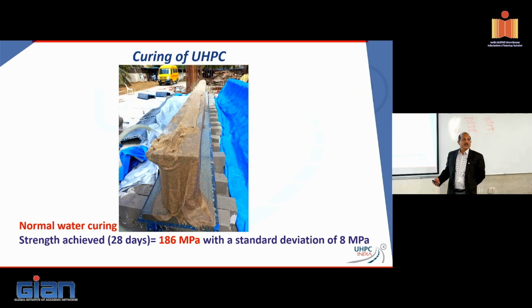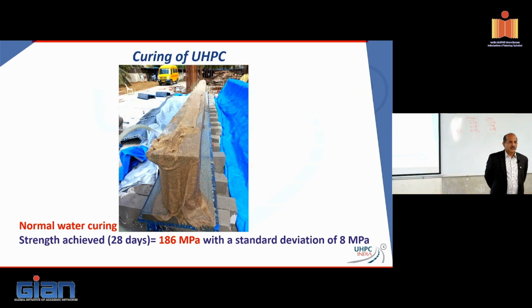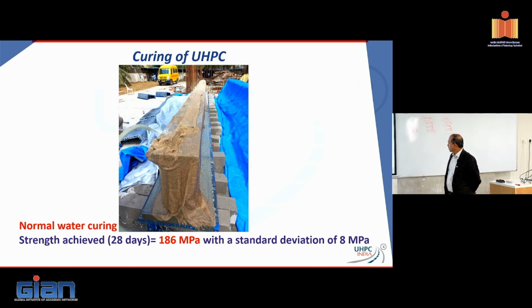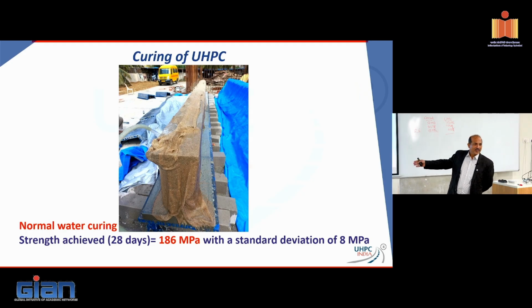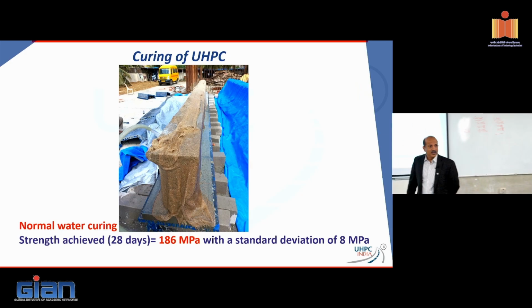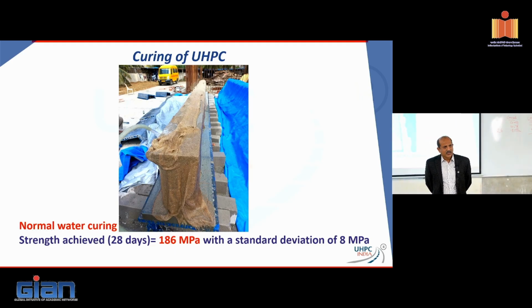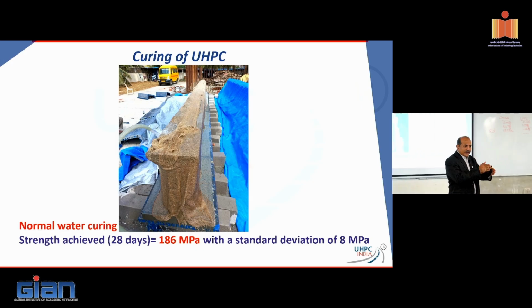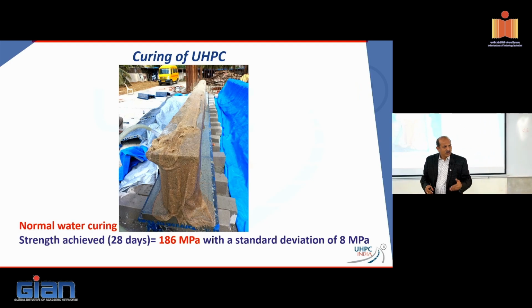Sir, why do we have a higher standard deviation? Does that depend on the strength of the concrete? Yeah, I would say, with normal concrete you might not want to see an 8 MPa standard deviation, but when you're talking of strengths in the range of 150 to 200 MPa, that number is not big. Why do we expect the material to be so homogeneous? See, there are other parameters. It's probably not just about the materials. Even if you get the best molds out there, there are so many situations on the site, like how the person is putting things in there. Are you getting a perfect 90 degree angle on the cube? Are all the faces of the cube really flush, so that you don't need to grind anything at all? So there are certain other parameters that come into play, and so those standard deviations or those numbers are going to be slightly off.